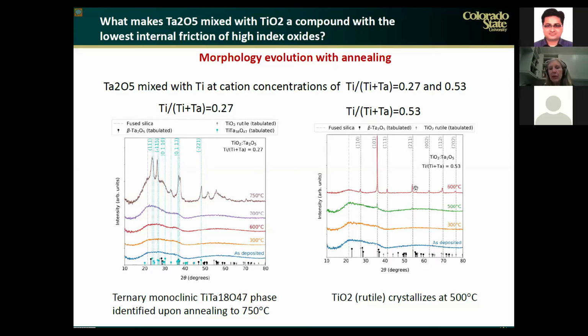Instead, if we look at the other alloy with a higher cation concentration, we see that as we anneal, the very first observation of crystallization is at 500 degrees C, and this peak corresponds to titania crystallizing in the rutile phase.